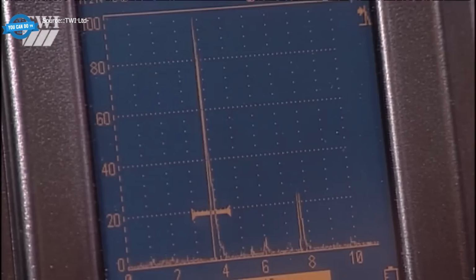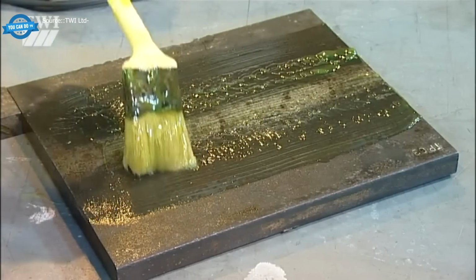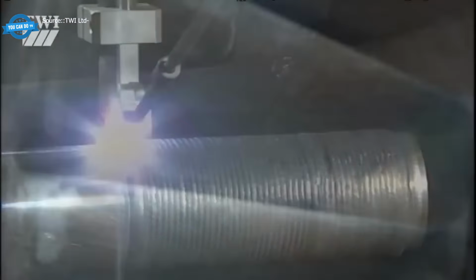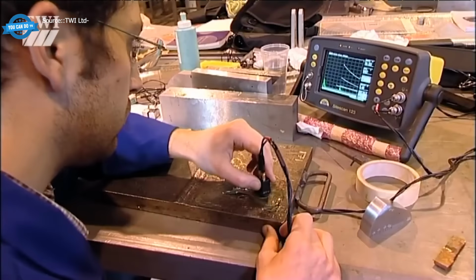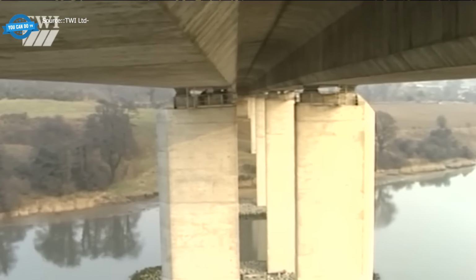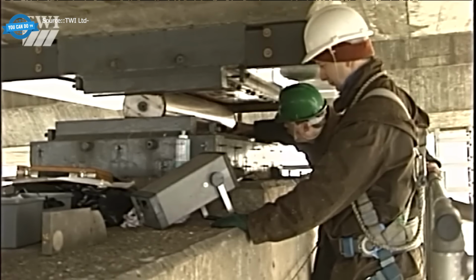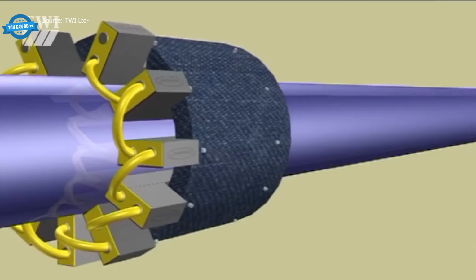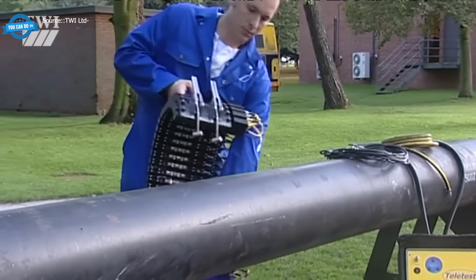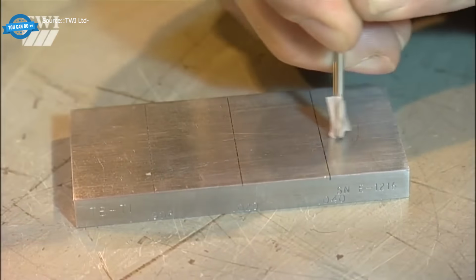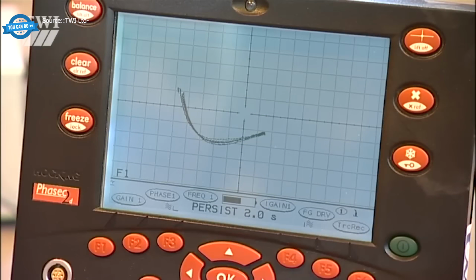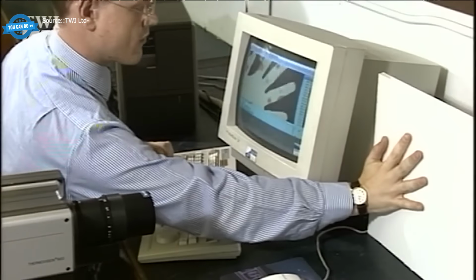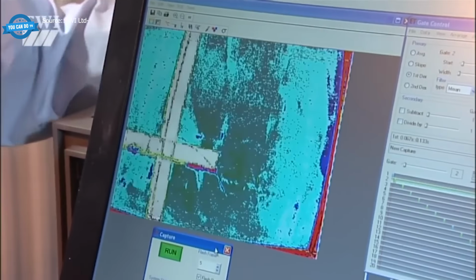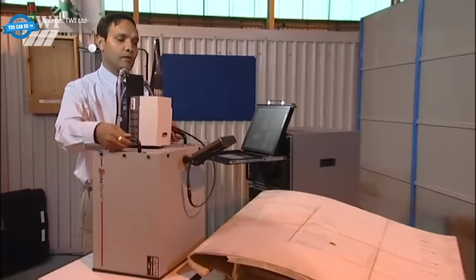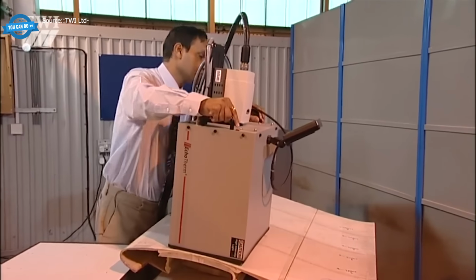Ultrasonic testing sends high-frequency sound waves into the casting and listens for echoes. Any internal discontinuity bounces the sound back, and the return time tells the inspector how deep the flaw sits. Phased array systems steer the ultrasonic beam electronically, mapping large sections of a weld or a casting in one pass. Eddy current testing uses induced electrical currents to find surface and near-surface cracks in conductive materials. Thermography spots hot and cold anomalies with an infrared camera. Every method has its niche. No one method catches everything.